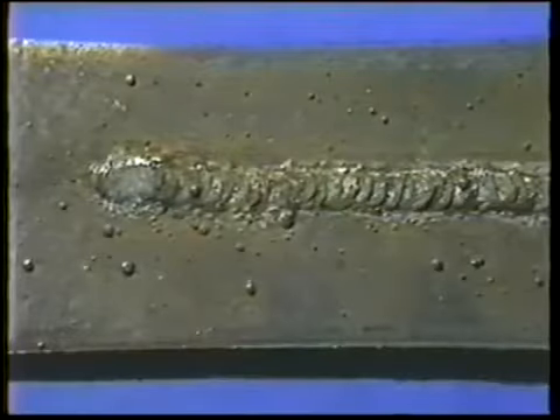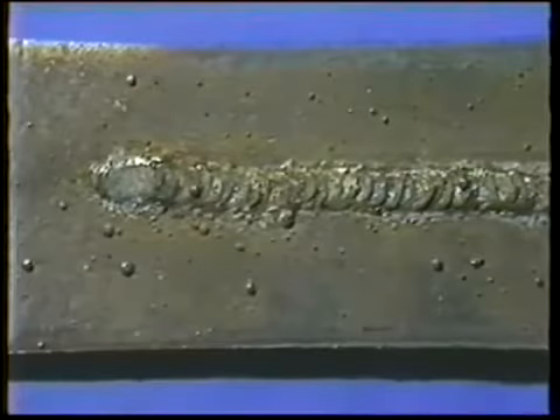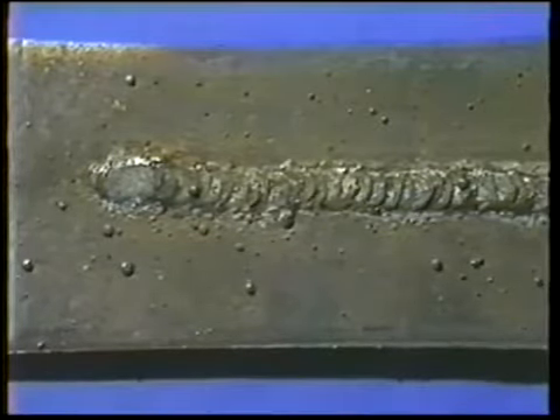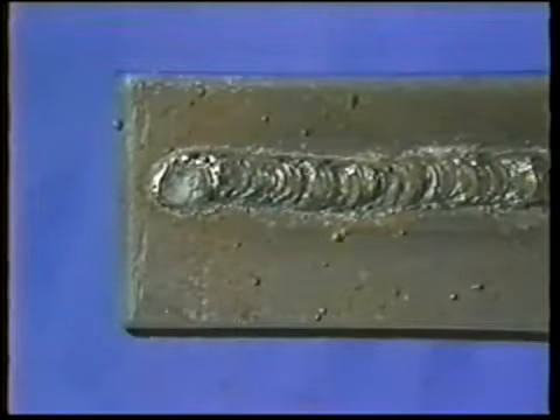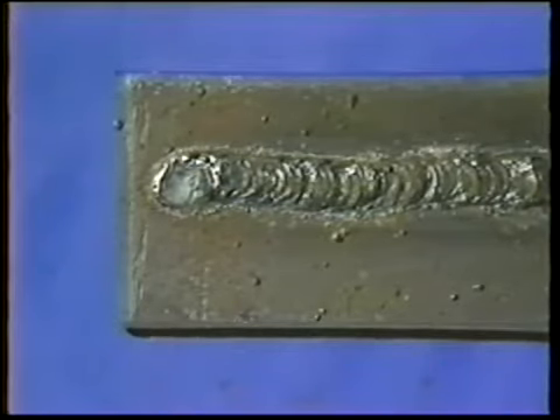If the travel speed is too fast, the molten metal does not stay molten long enough, trapping gases and slag. The ripples will be pointed and narrow, with irregular penetration and undercut on each side of the weld bead. If the travel speed is too slow, the molten metal piles up. The bead will be high and wide, with considerable overlap and deep penetration.